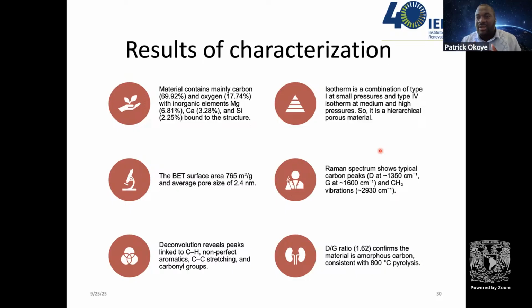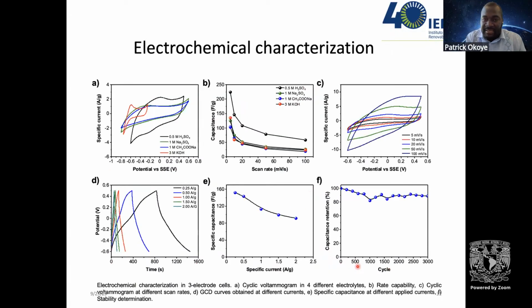And the isotherm is a combination of type 1 at small pressure and then type 4 at medium to high pressure. The BET surface area here is not very large, it's about 765 square meters per gram, but the pore size is within reach. Our Raman spectroscopy shows a typical D band and G band. And from the deconvolution, the ratio between the D and G band is 1.62, which confirms that the carbon material we produced is amorphous. And of course, it will be amorphous because it was produced at about 800 degrees Celsius.